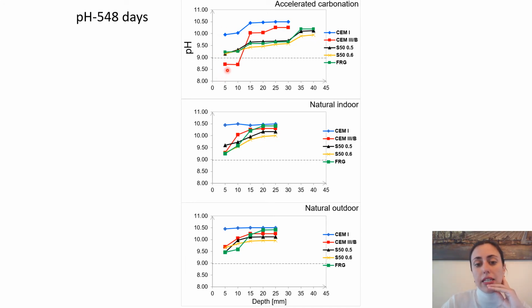And we can see that on the very top surface, the lowest alkalinity is actually in alkali activated concrete, whereas for cement 1 it's higher, while for cement 3B it is even lower than for alkali activated concrete. When we look at natural indoor and natural outdoor, they all are above 9. The pH is above 9, and it actually slowly drops and stays high in the really inner part